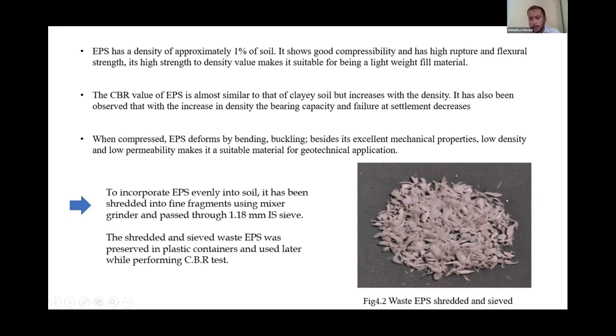So in our work, waste EPS out of cups and plates were used, which were shredded with the help of a mixer at my student's home, or the blenders, you can say. And this shredded EPS was stored in plastic containers when not in use. These were passed through a 1.18 mm sieve. And the sample to be tested for CBR, as per the codal provisions, has to be passed through a 4.75 mm sieve. So thinking about this combination, we thought that there would be a good interaction, and we wanted to see how we could get some beneficial results.